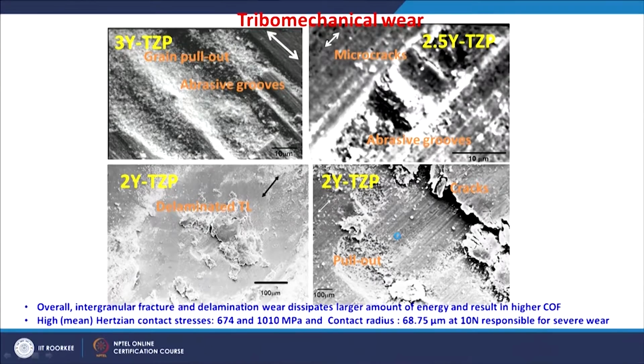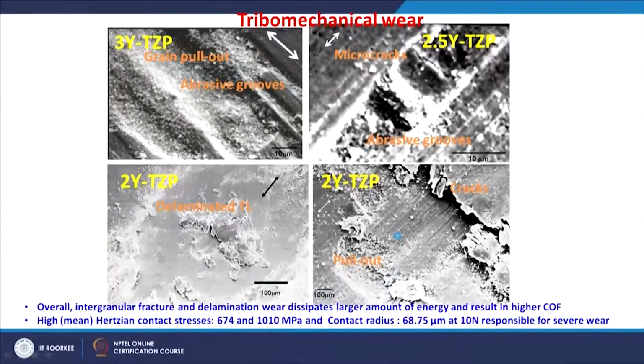So, let us understand the mechanism of these materials. You can see the worn surfaces of these ceramics after fretting show mainly mechanical wear. For example, for the 3% yttria stabilized zirconia, the worn surface is characterized mainly by deeper and wider abrasive grooves as well as a lot of grain pullouts. This is mainly because of the mechanical wear that is characterized by this pullout and abrasion.